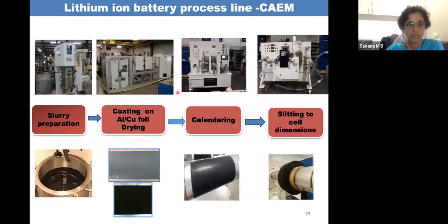Now let's see the process steps in a lithium ion battery process. First, what we do is slurry preparation. The slurry on the left downside consists of the active material, that is the electrode material, which may be a cathode or the anode, and carbon black and the binder. So this is a slurry. Using a coater, we coat it over a current collector, and we dry that.